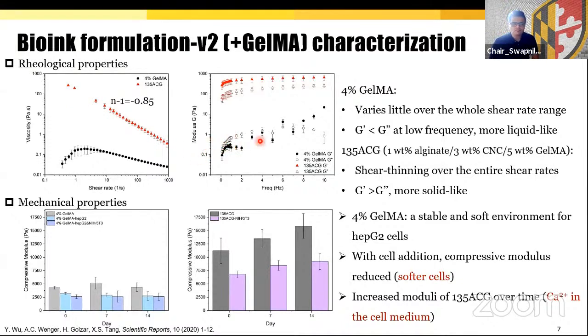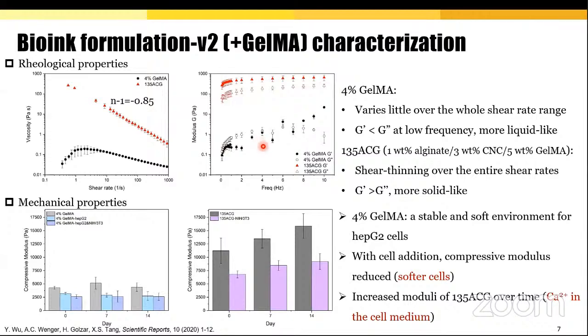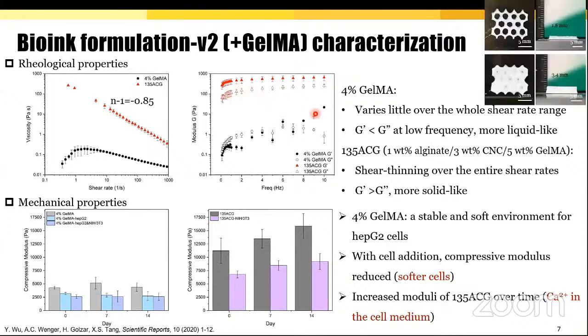In 4% GelMA, the viscous modulus was higher than the elastic modulus at low frequencies and only around 1 pascal, indicating the pure GelMA was more liquid-like at low frequencies and not suitable for bioprinting. Thus, we deposited GelMA in middle cavities, which was supported by the honeycomb structure. The elastic modulus of 135 ACG was higher than the viscous modulus and over 100 pascal, meaning it's more solid-like and can produce scaffolds with good structure fidelity. By using 135 ACG, structures with favorable fidelity up to a height of 1.8 millimeter is obtained, but spreading and